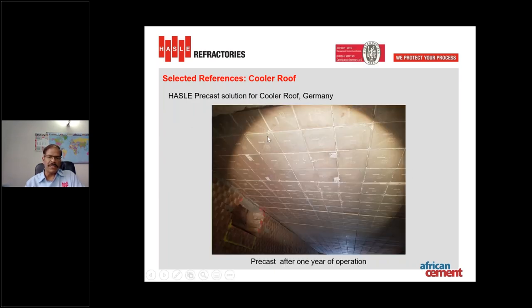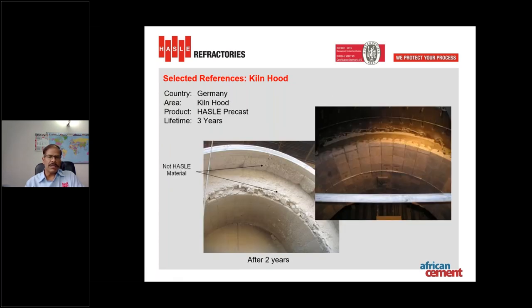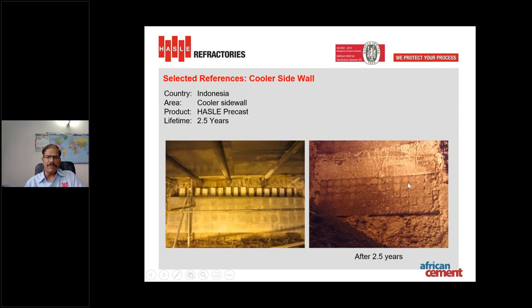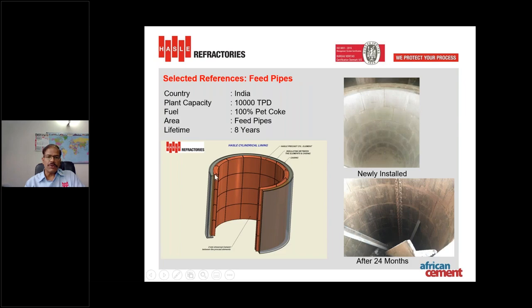Same way, we can do the precast lining in cooler roof area, in kiln hood area, in cooler side walls area, with excellent performance, which cannot be achieved by normal low cement castables. We can also produce this precast lining for feed pipes. This is a case story from one of the plants in India running on 100% pet coke, and this plant was facing a lot of coating issues in feed pipes. This is the condition after 2 years of running. You cannot see any coating trace on the feed pipe refractory. The lifetime achieved by this lining can be 8 years or up to 10 years. There are some plants which can achieve 10 years life with this precast lining in feed pipes.